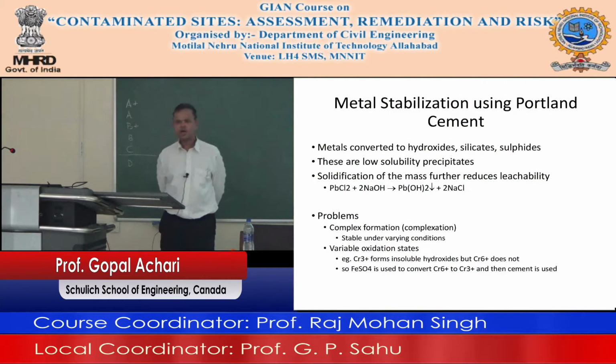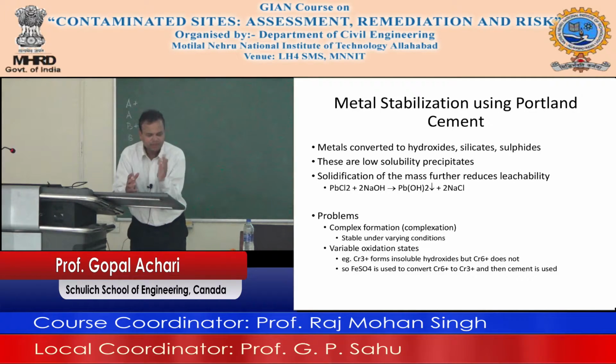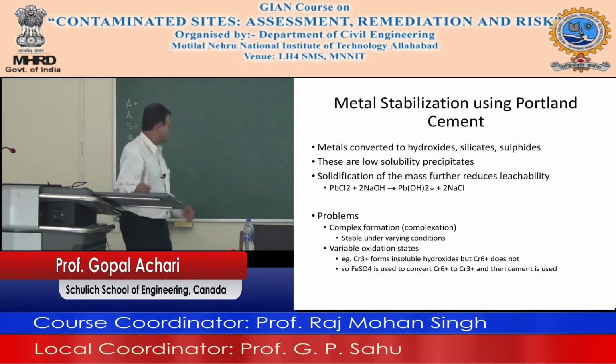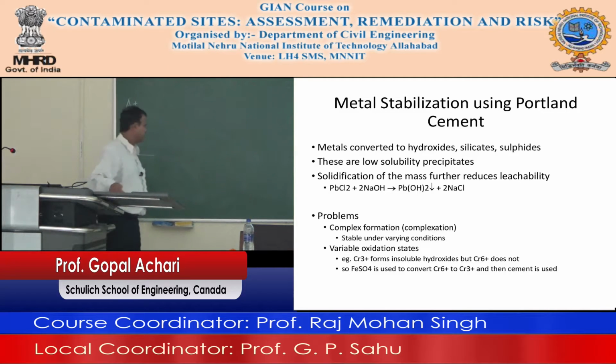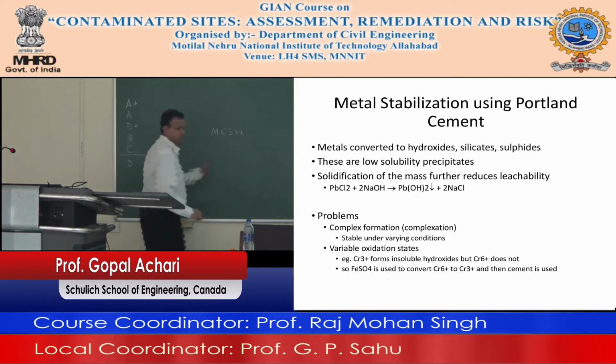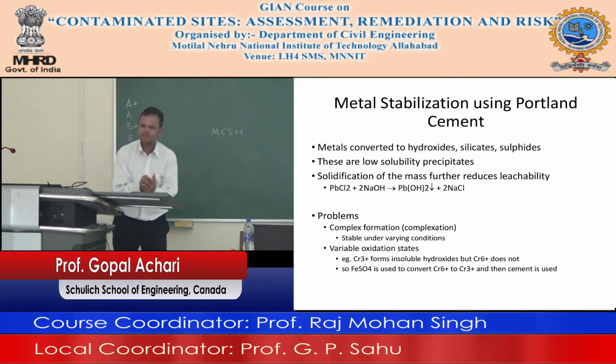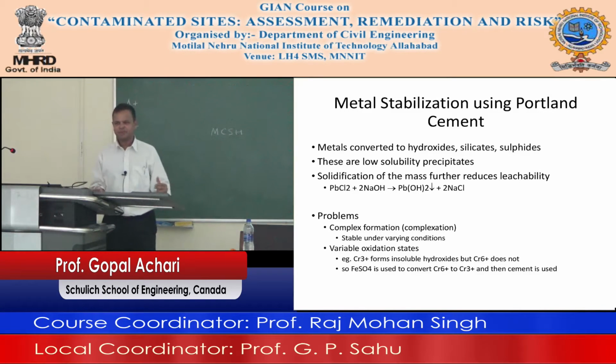So there was a thought that maybe because you fix it in cement, it remains in a low permeable matrix, right? But actually cement binds with the calcium silicate hydrate to form metal calcium silicate hydrate. This is a bond, okay? It's not just sitting on the periphery fixed in a low permeable matrix.